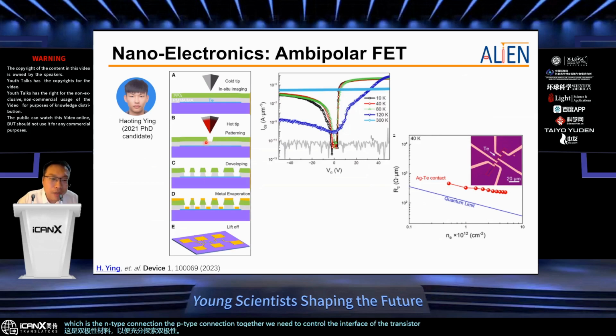As I mentioned in my previous work, this sacrificing layer has to be etched by corrosive chemicals. But with the help of this student, Hao Ting, he developed another sacrificing layer that can be etched by IPA and water, controlling the ratio of IPA and water. This is less corrosive than before. Then we can preserve the interface of this sensitive tellurene material and observe the bipolarity of the field effect transistor. As you can see, the P-type conduction and the N-type conduction both achieve very large on-off ratios. And we can get this bipolarity because of the interface.